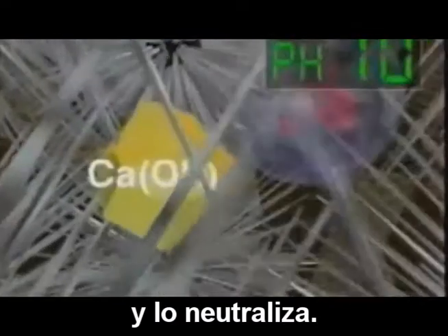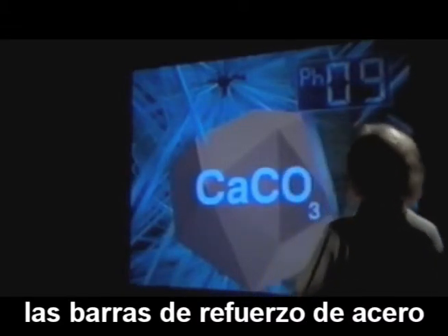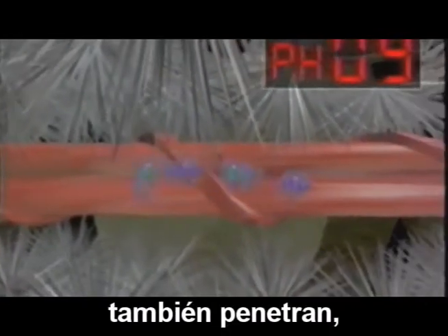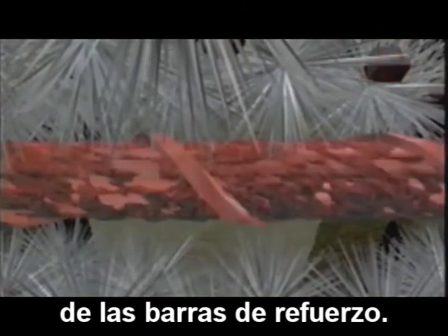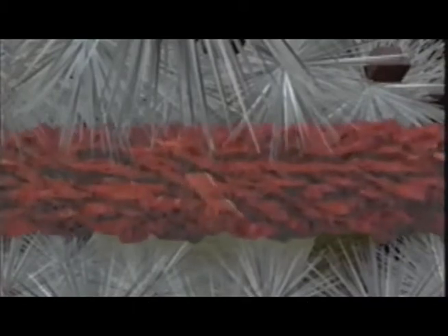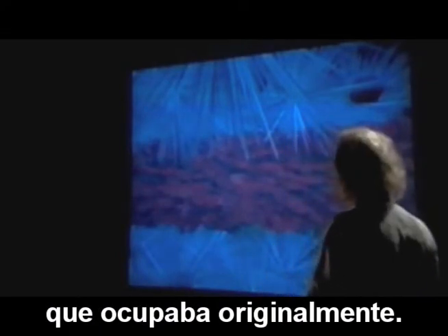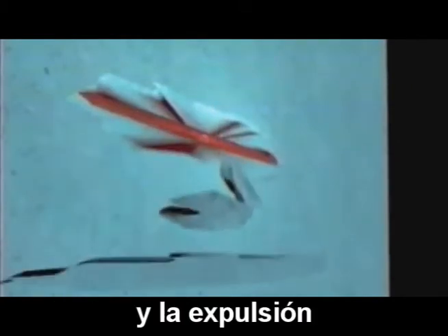When the carbon dioxide present in the air penetrates into the concrete, it reacts with calcium hydroxide and neutralizes it. And with a pH below 11, the steel reinforcing bars inside the carbonated concrete are no longer protected. From the outside, water and oxygen also penetrate, thus increasing the rusting reaction of the reinforcing bars. The rust which forms occupies a volume of about 6 times more than the metal from which it originated, and so causes the cracking and expulsion of the concrete cover.